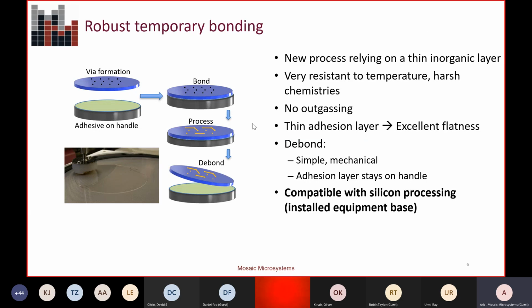So some very important characteristics of this temporary bond. It's a very thin inorganic layer, so it's very resistant to higher temperatures and harsh chemistries. We process our wafers with HF, with SC1, SC2 cleaning. Again, you can go to 450 degrees C, even higher, and you don't have any outgassing. So it's very attractive for introducing with standard semiconductor processes.